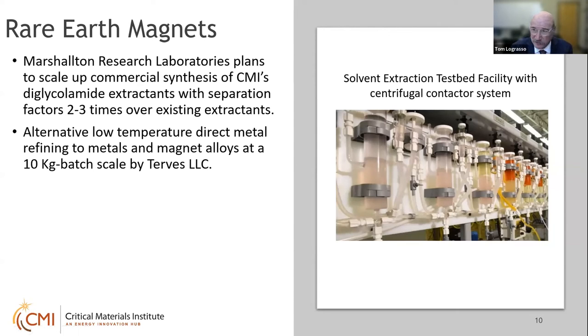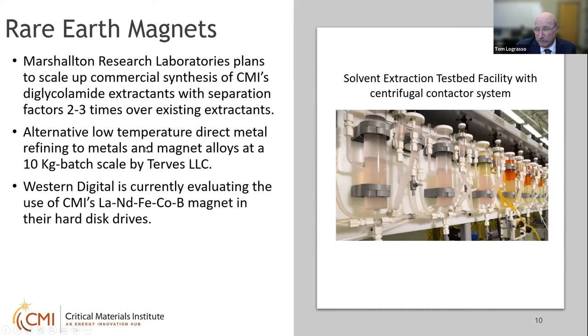We're also looking at direct, alternative ways to refine rare earth oxides to metals and magnet alloys, preferably along routes that require less energy, low temperature. Most of the rare earths are produced by electrochemical molten salt processes, and we're looking at new, more continuous thermal metallic reduction methods. And again, tested out at the laboratory, now being developed by Terves LLC at the 10 kilogram batch scale.